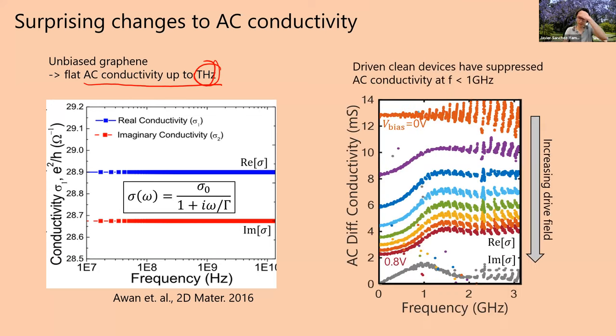So we were very surprised to see that if you take a clean graphene device and apply voltage across it, the AC conductivity begins pretty flat, but then as you apply increasing drive field, this differential conductivity as a function of frequency rolls off at low frequencies. So there's a suppression of the AC conductivity at low frequencies. Also completely unexpected. There's this suppression here.